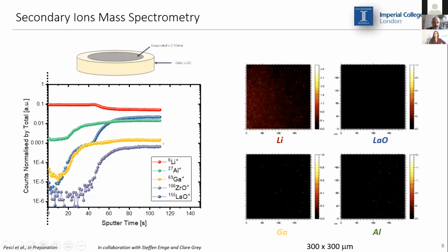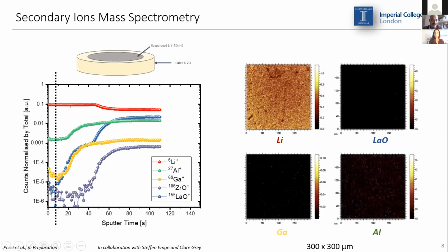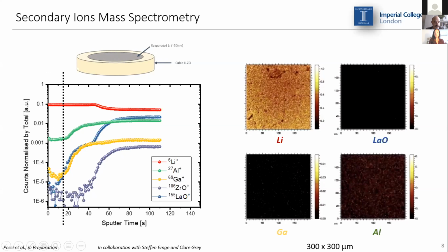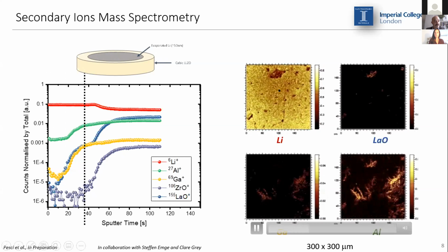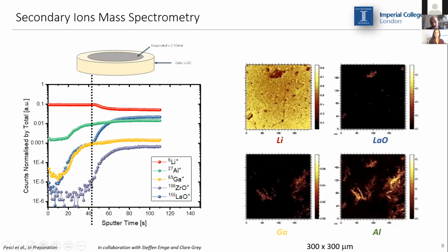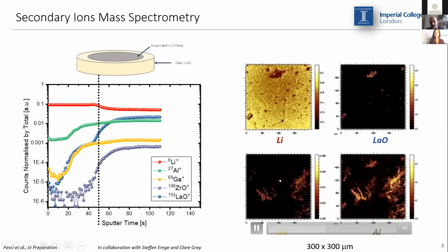I'm just going to give you an example here of how SIMS works. In this experiment, I was looking at an LLZO pellet on which we evaporated a very thin layer of lithium. With SIMS, I was trying to go through the lithium electrode to the LLZO pellet and see how the composition was changing at the interface. From the depth profile, when we are on the lithium, we have a depletion of all the other garnet components, and from the elemental maps we only see a lithium-rich surface. However, when we go through the evaporated lithium, we see the appearance of other features.